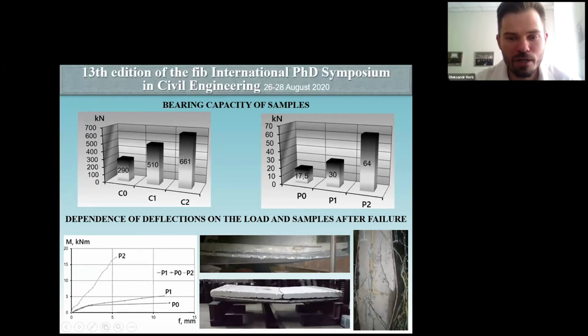If I understand, you talk about moving of a concrete block separate from the steel. In this case, when we talk about profiled flooring, we can use profiled flooring with stamps, not with a very clear surface, but a surface with some stamping. And in this case, the area of connection between steel and concrete will be bigger. And in this case, sliding of the concrete block relative to the steel in the longitudinal direction and in the perpendicular direction, I think will not be so big.